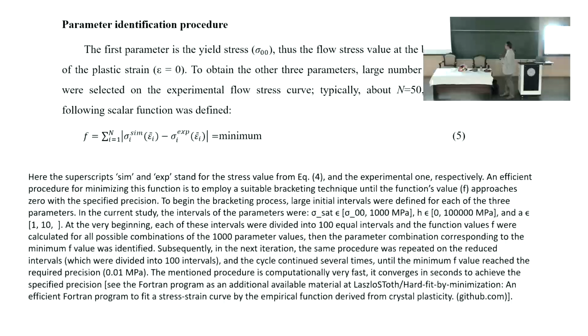Very large. And for the A exponent, between 1 and 10, actually 1 is not suitable. So 1 and 10. And then this initial interval is cut into 100 small intervals, and in each interval, at each point, calculate how much is the function value. And there are 100 values for 3 parameters - 100, 100, 100. All combinations you calculate, it's a loop, easy to do.